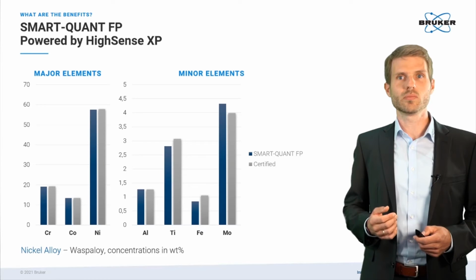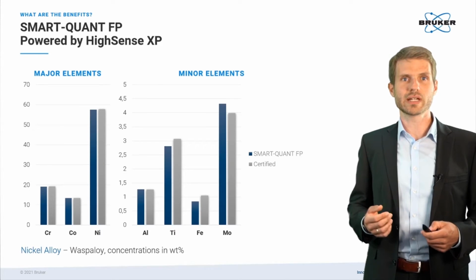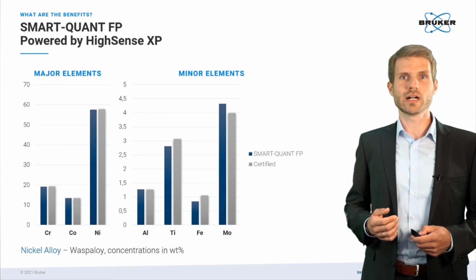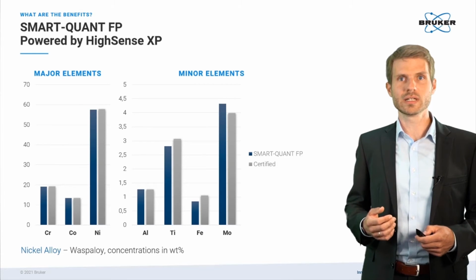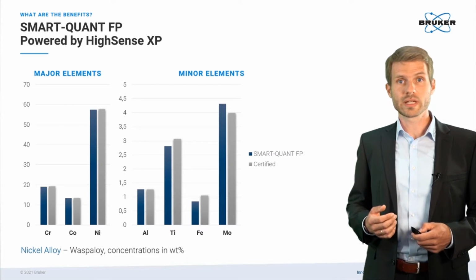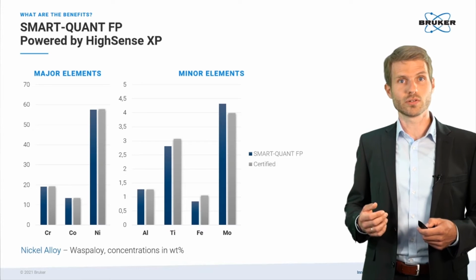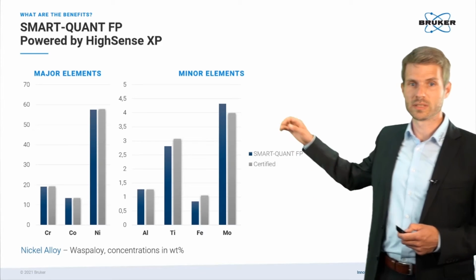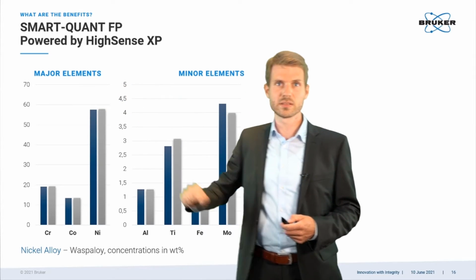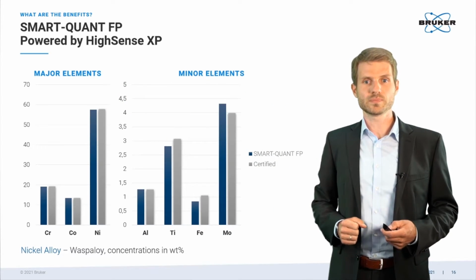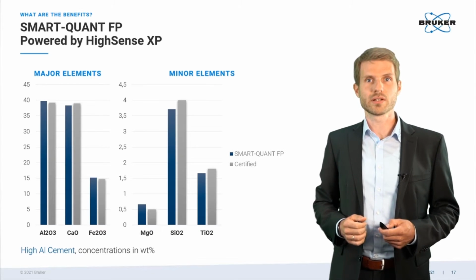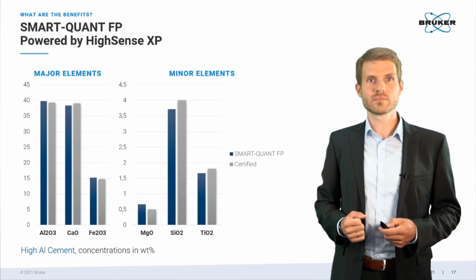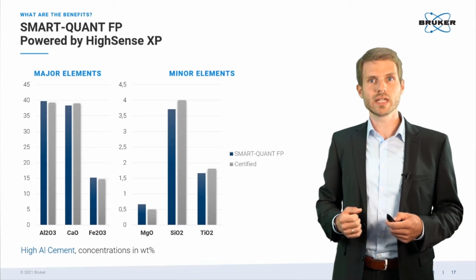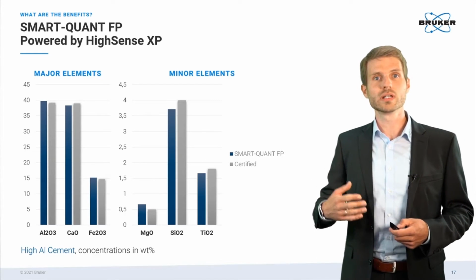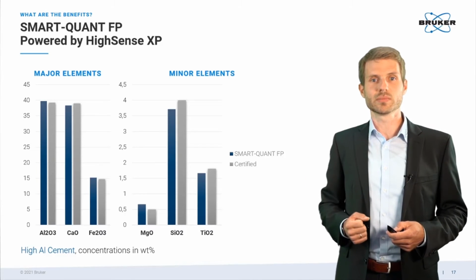Now let's take a look at what SmartQuant FP with the new detector can do for you. Here I'm showing results for Waspaloy, so nickel alloy analysis performed with SmartQuant FP. Clearly, our standardless solution can achieve an outstanding accuracy, for instance, for nickel, chromium, and aluminum. Over here you have the nickel, for instance. And we have also another example, and this is the second example here. This is for high aluminum cement. Again, the results are quite impressive, even for the major elements, but also for the minor elements like the light element magnesium here.